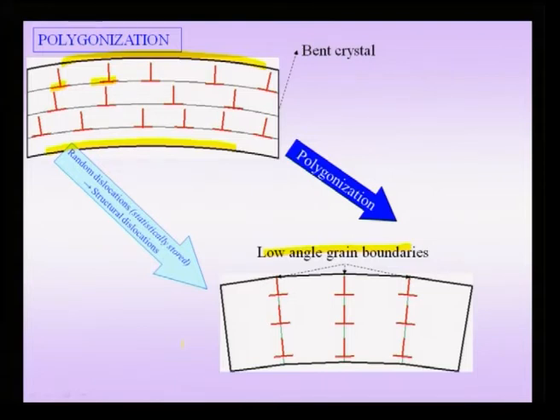Now, during recovery, of course, the thermal energy is not so high, so these dislocations cannot move over large distances, but they can come together in close vicinities. That means a few dislocations lying in this regime can all come together, which are of course on different slip planes. Say for instance, these three dislocations can all come together and form a low angle grain boundary. This phenomenon overall is called polygonization, wherein originally there was a single crystal, a single bent crystal, as you can see here. So, this is my single bent crystal.